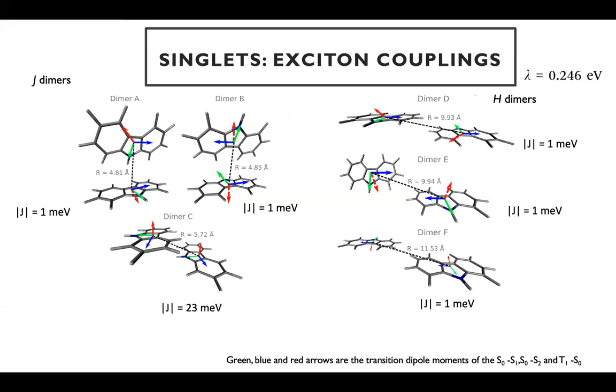When we move to the solid, we will have different kinds of dimers. We will have different kinds of configurations of one molecule with respect to the other. And you will see that in these systems, the values of the exciton couplings are extremely small. The largest value of exciton coupling is 23 milli electron volts, which is a very small value.